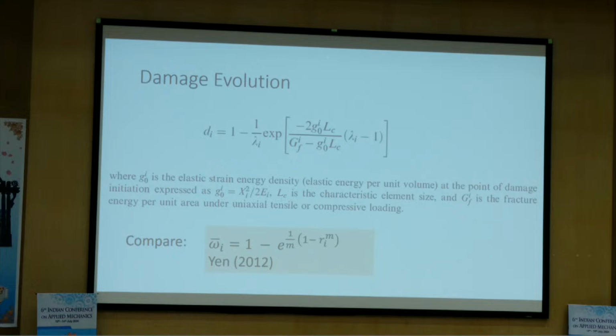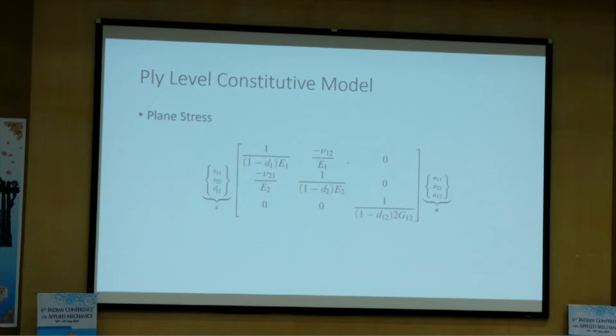So there is an initiation criterion, growth criterion, strain rate dependency, and then you degrade the modulus. That's all, the 4 methodologies that make the composite model. You can introduce all types of failure and capture the failure damage mode with the appropriate equation and perform experiment, calibrate the constants, and tune the constants with the code simulations, and you are moving forward. And again, see that? Same thing, right? Young's modulus, shear modulus degraded. This is the plane view. Plane view, you have 2D model. Okay, but then the build up is 3D. All right.